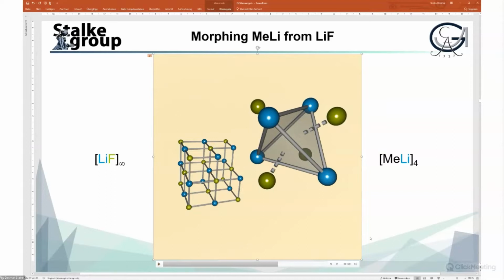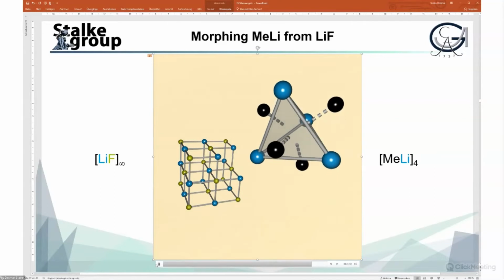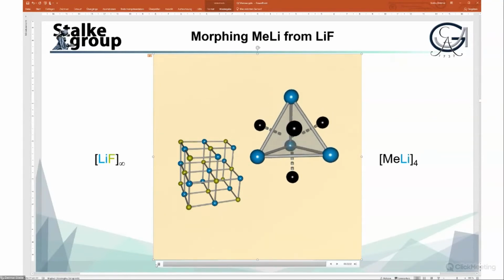Then we have almost the structure of methyl lithium there. We just need to change the color from the halide to the black of the carbon, and there you go. You have morphed the methyl lithium structure from the lithium halide.